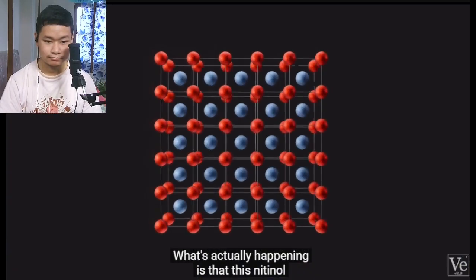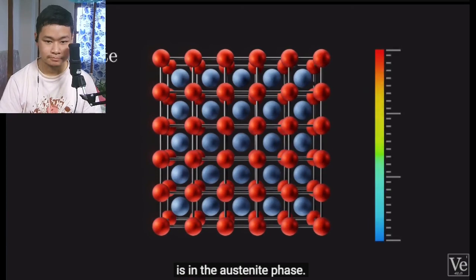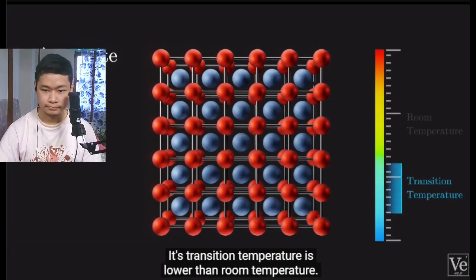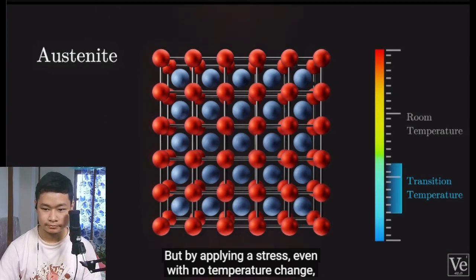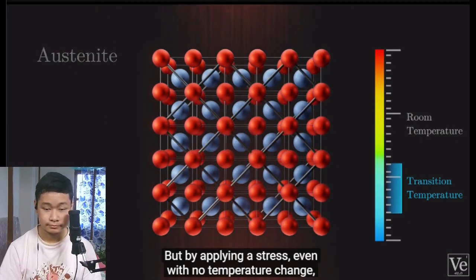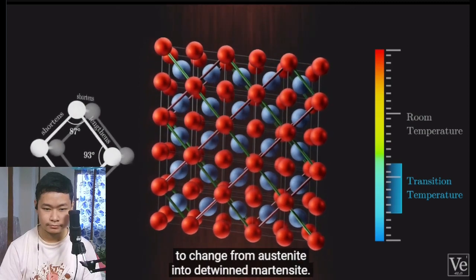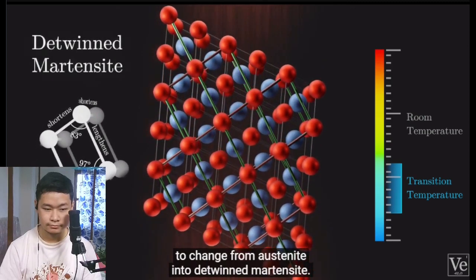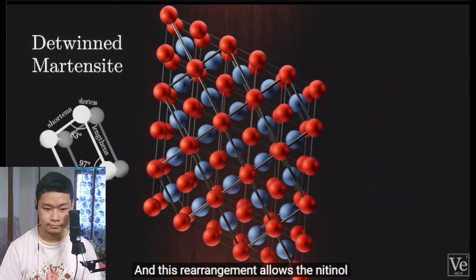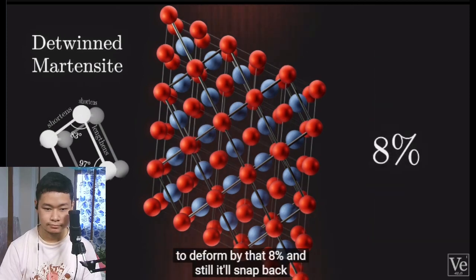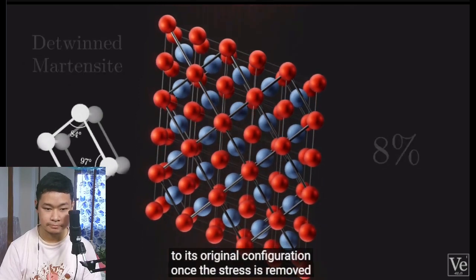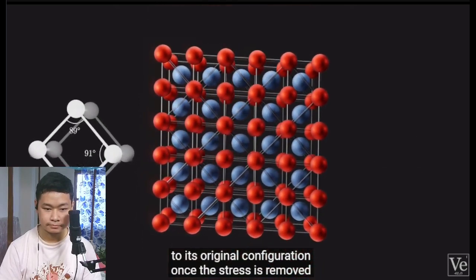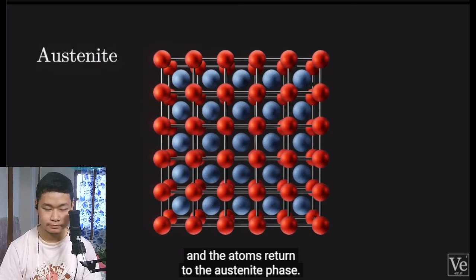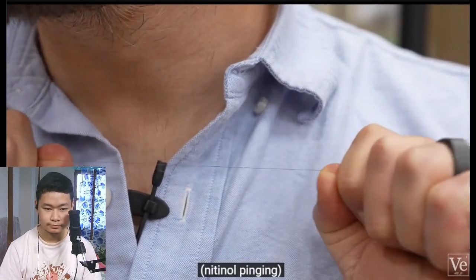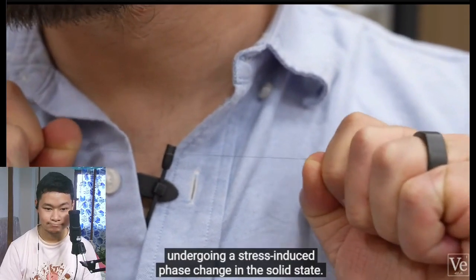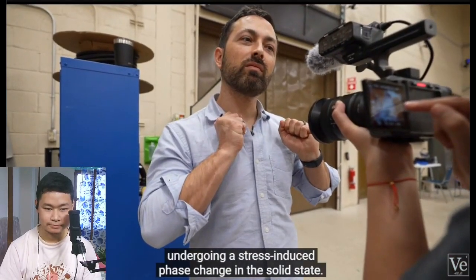What's actually happening is that this nitinol is in the austenite phase. Its transition temperature is lower than room temperature. But by applying a stress, even with no temperature change, you can force the crystal structure to change from austenite into detwinned martensite. And this rearrangement allows the nitinol to deform by that 8%. And still, it'll snap back to its original configuration once the stress is removed and the atoms return to the austenite phase. That sound you're hearing is the material undergoing a stress-induced phase change in the solid state.